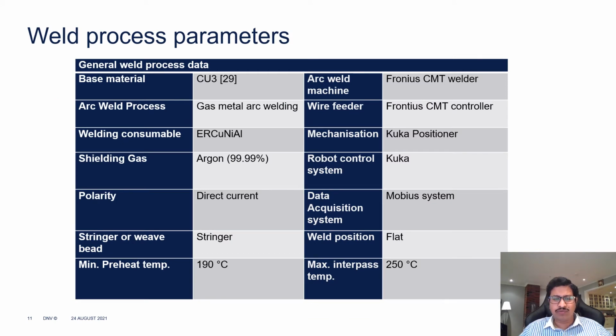The weld process parameters we used: the base material was copper nickel alloy. The arc process is gas metal arc welding, and the welding consumable was standard copper nickel aluminum bronze. If we use this welding consumable, we do not require a post-weld heat treatment on the process. We also use shielding gas argon 99.99%. We use a stringer bead, and we maintain a minimum preheating of around 190. The arc weld machine was Fronius CMT welding, the feed wire was by CMT control, and data acquisition was done by a Mobius system. The maximum interpass temperature was maintained at 250 degrees centigrade.